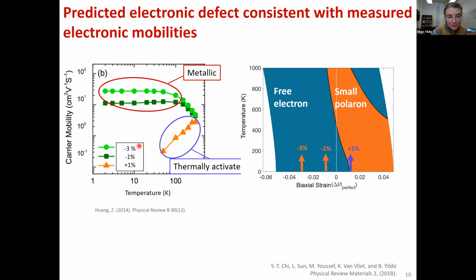So in the compressive strain regime, so -3, -1%, the slope of conductivity versus temperature tells us that this behavior is metallic. And that strain regime is consistent with our prediction of free electron being the dominant electronic defect. And if we look at the tensile data, that is +1% tensile strain, the conductivity is thermally activated, and that is also consistent with our prediction of small polaron that should show this thermally activated conduction.